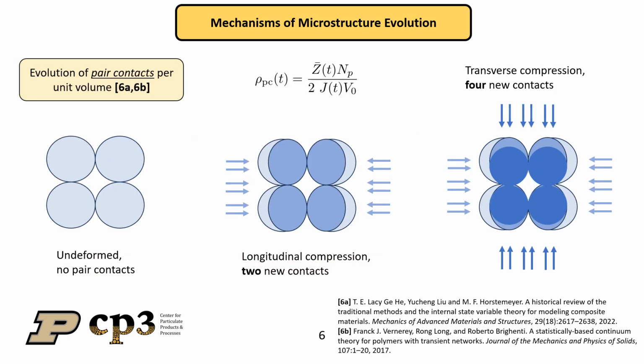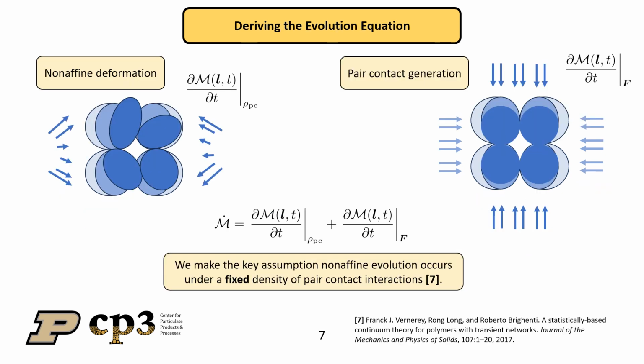Another key aspect of microstructure evolution is the evolution of pair contacts. And the way we examine the evolution of pair contacts is in terms of the volumetric deformation. And what we can see here is that when we apply volumetric deformation laterally and in the transverse direction, we find the formation of new mechanical contacts. And thus we decouple these mechanisms, where we have just the formation of pair contacts from point contacts as well as the non-affine deformation of existing contacts. Using those two mechanisms, we now show an overview of how to derive an evolution equation for M.